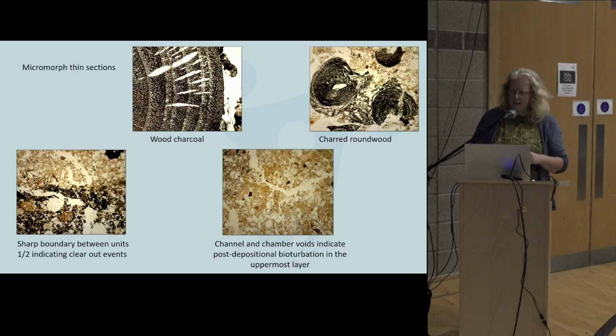The in situ fires and the presence of large numbers of phytoliths and wood charcoal indicate a mixed fuel regime, which includes wood and grass fuel, and this would suggest a low temperature smoky fire. This fuel would imply that the fires are not only deliberately set, but appear to have been quite well controlled. They're designed to burn at a constant temperature, which is good for maintaining heat and drying out large quantities of grain and reducing the risk of charring or the whole kiln going up in smoke.